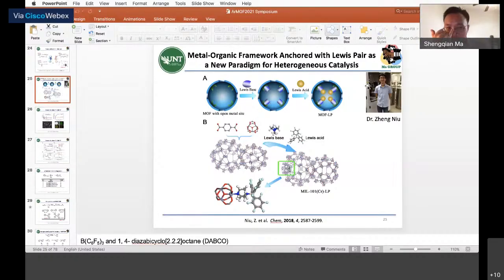Okay, that's a good question. I think so far, you are talking about direct air capture, right? Direct air capture is now a very hot topic. Currently, there are several types of porous materials being explored for direct air capture. One of them, of course, is amine grafted into the MOF or into some other materials like mesoporous silica material, etc. That's basically based on chemical absorption to form this bond, carbamate or whatever. You can have very high uptake at a low pressure, but the thing is, the heat of adsorption is very high. Typically it will be over 90 or even 100, right? Like some of the work reported by Jeff Long in the MOF.